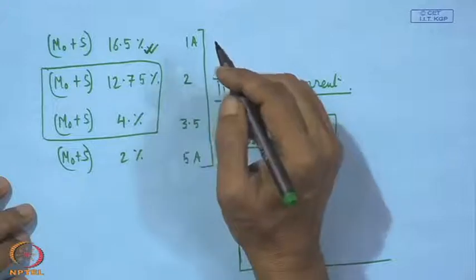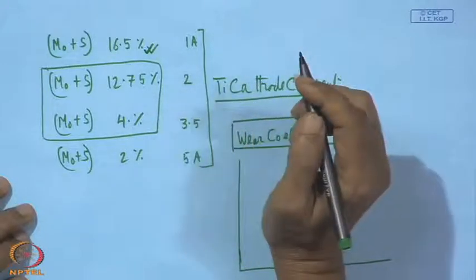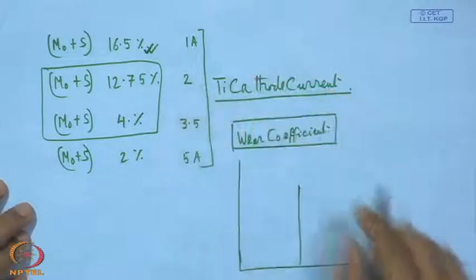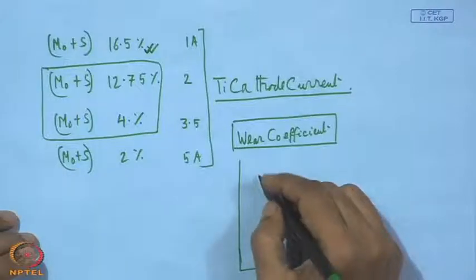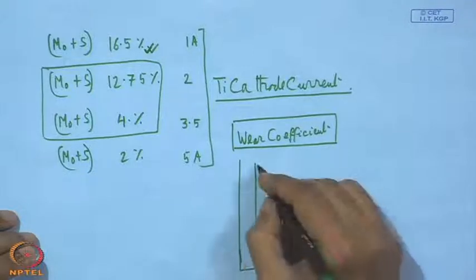in this case we can get a good value of wear coefficient, and this is just a balance between titanium nitride content and that of MoS content, and at the same time the coefficient of friction can also be obtained with a rather favorable value. So, this is actually on one side the coefficient of friction, and on the other side this is also the wear coefficient. Now, considering these two, what we find is that the wear coefficient will be quite high on this side.